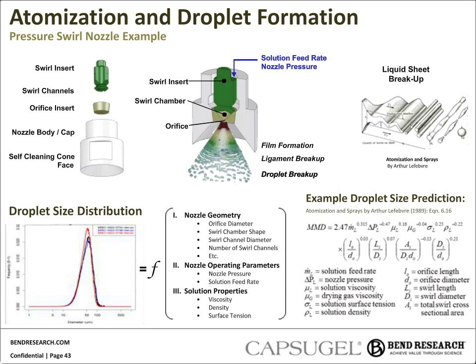The droplet size distribution produced by the nozzle is a function of nozzle geometry, things like the swirl chamber design, open area, the orifice size, and even the surface finish of the orifice and swirl chamber. And also the nozzle operating parameters like nozzle pressure and feed rate. And then lastly, the solution properties: viscosity, density, and surface tension.